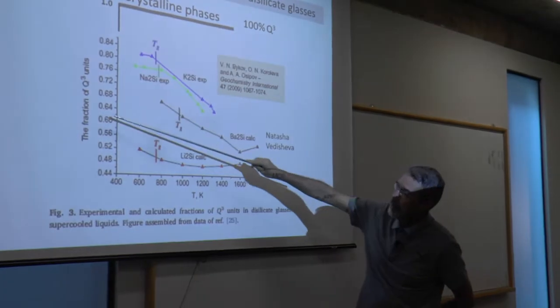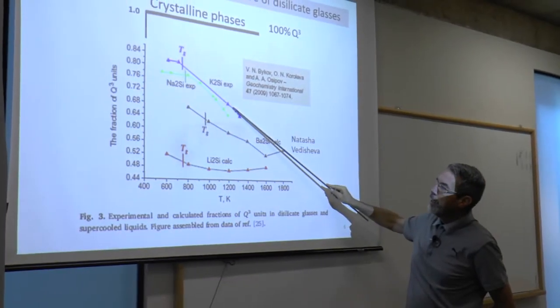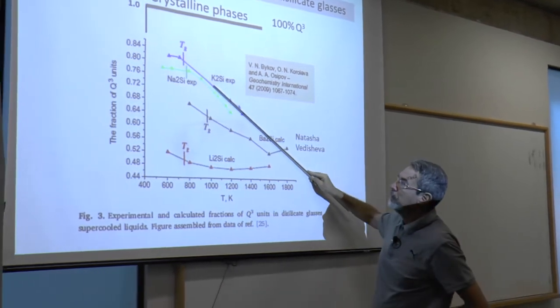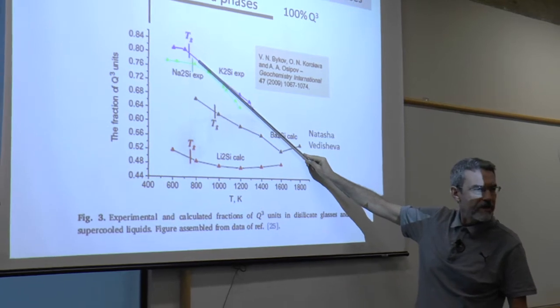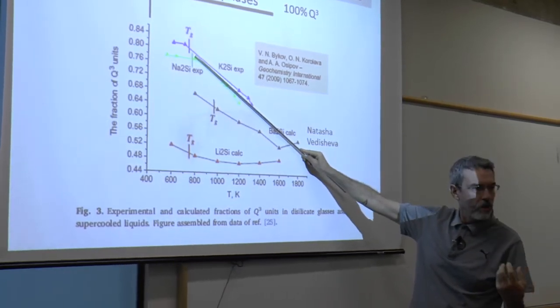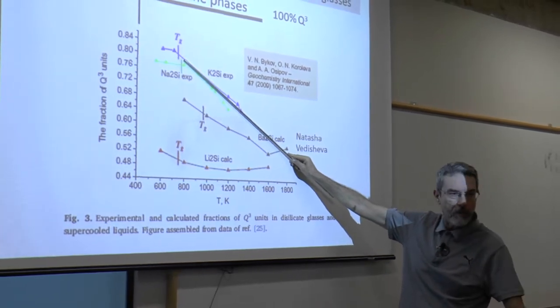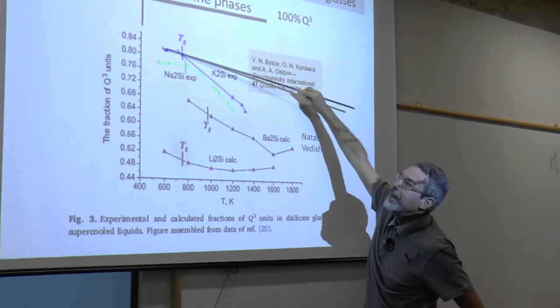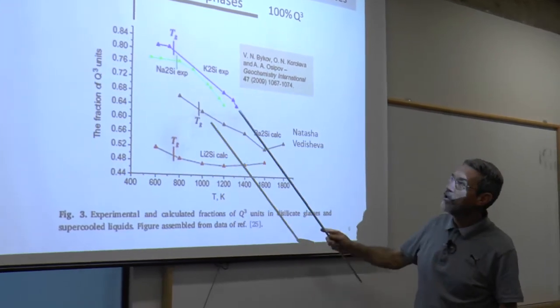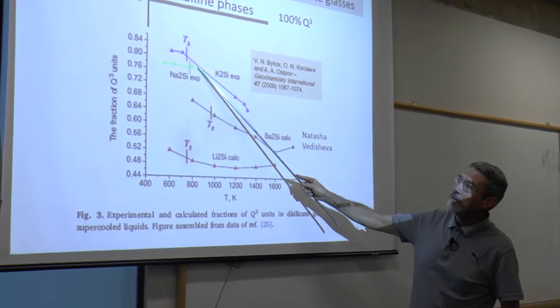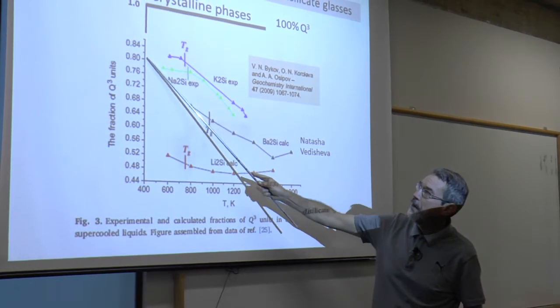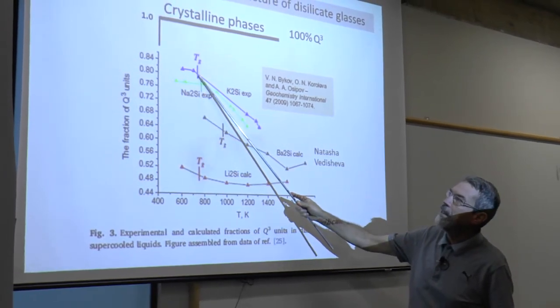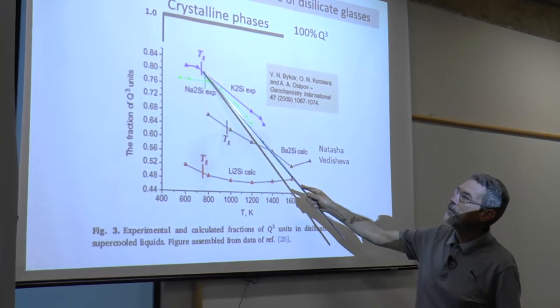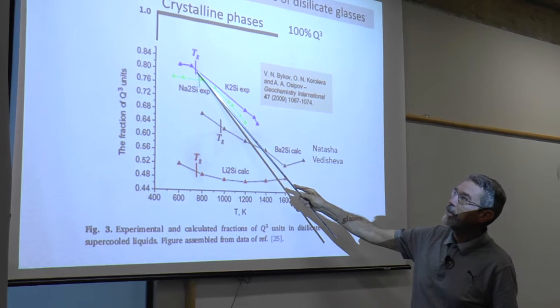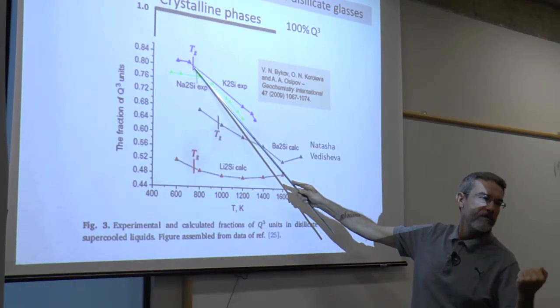But if we look at the glasses, let's take the potassium silicate glasses, the fraction of Q3 increases with temperature, so the structure changes with temperature. This is one way to look at the glass structure. There are several ways. I'm going to show you in a minute. But at TG, it freezes, as we expect. So for this particular glass, we have about 82% at TG here, 82% or so of the tetrahedra are sharing 3 corners.